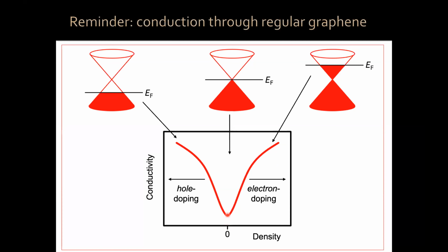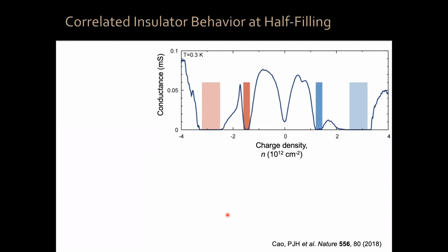Let me show you what happens when you measure magic angle graphene. So these are measurements of the conductance versus charge density. This charge density is in units of 10 to the 12 electrons per square centimeter, okay, because it's two-dimensional. And this is a conductance in millisiemens. So in order to understand the way this looks, you can see this V shape near zero, near charge neutrality. That looks like regular graphene. But then you can see all kinds of crazy things, okay?